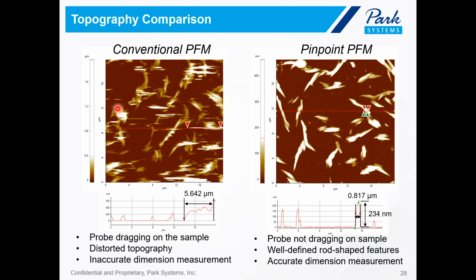From the conventional PFM imaging conditions, imaging artifacts can be seen throughout the entire scan area, indicating that the probe was scratching and dragging on the sample. We have distorted topography, and accurate dimension measurement of the features was very difficult, nearly impossible. To give you an example, here we draw a line profile along the red line, and here is the actual line profile. If we want to measure the width or the length of the rod, here is what we measure, 5.6 microns, which is obviously not the actual length of the rod, but an indication that the probe is dragging on the sample. So that is not an accurate measurement.